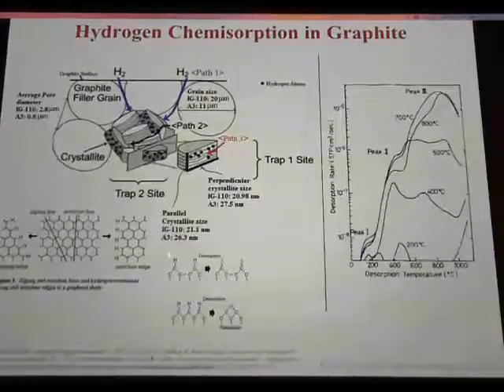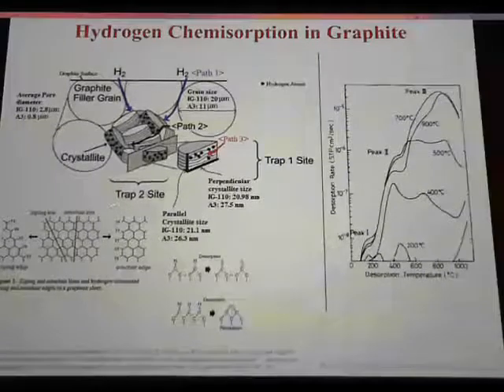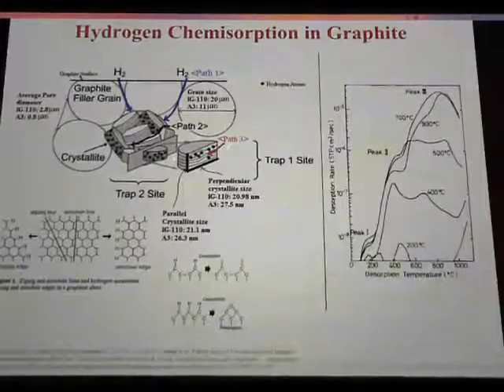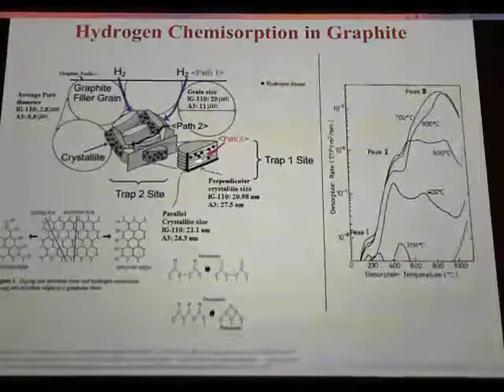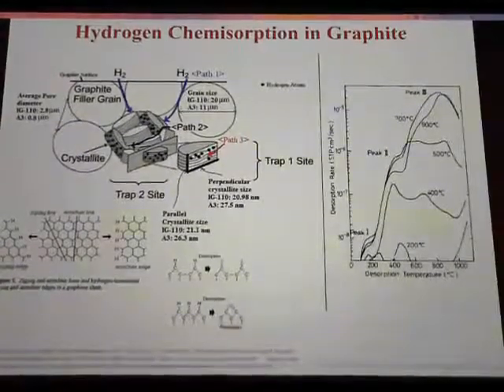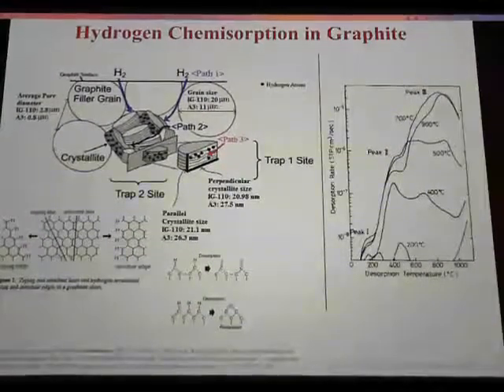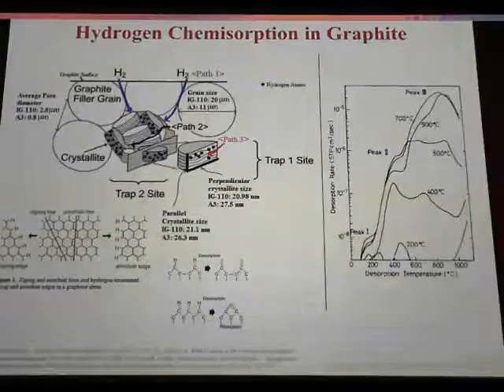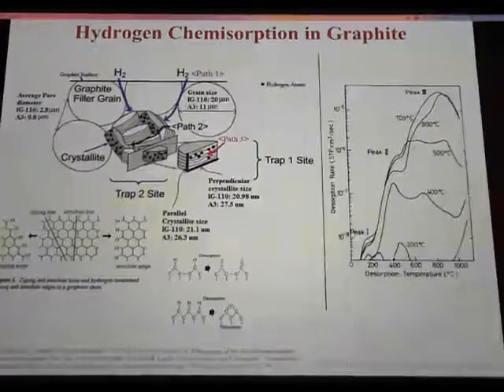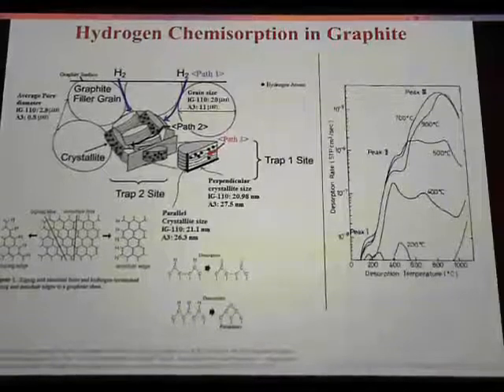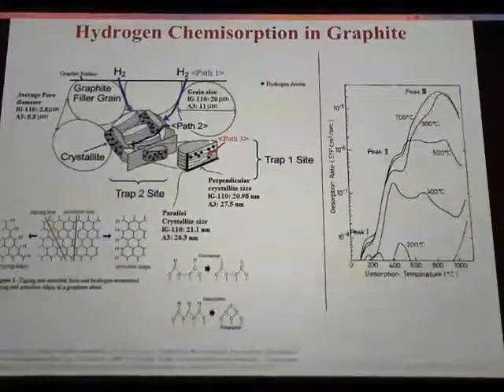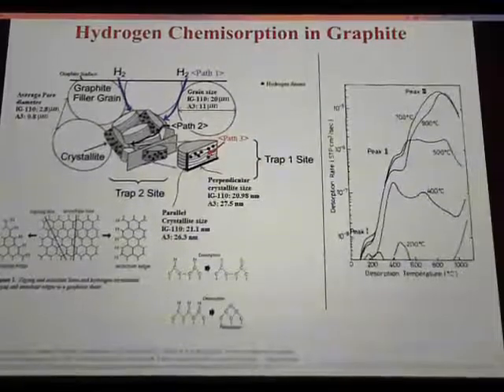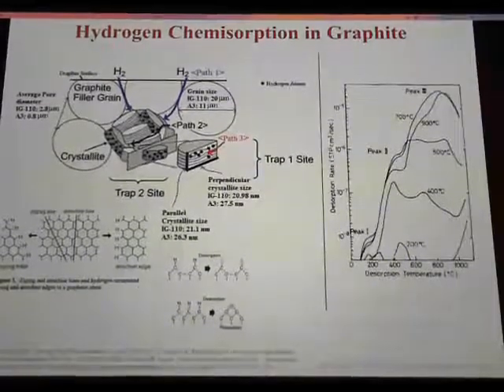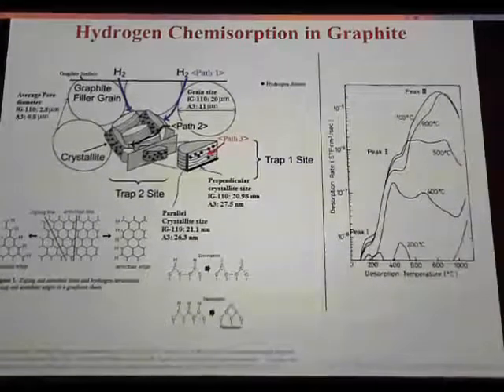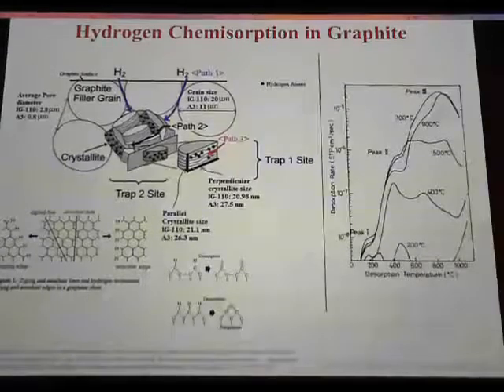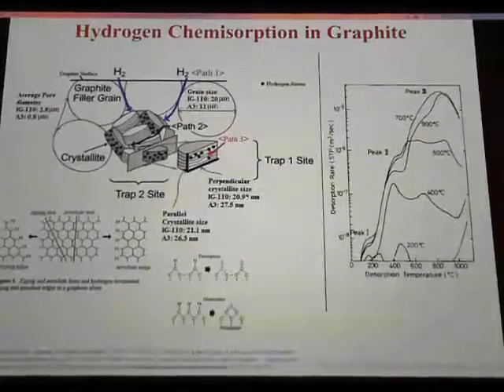And so then we have to talk a little bit about the structure of graphite. Graphite, you can think of it as a composite. It has grains of about 20 microns. And the numbers that you see here are from the microstructural characterization that we did on those two materials that I showed you. And so the nuclear graphite has grains of 20 microns, the matrix graphite has grains of 10 microns. And then within those grains, we have what we call crystallites. And crystallites are graphene sheets stacked on top of each other. And these crystallites are on the order of 20 to 30 nanometers